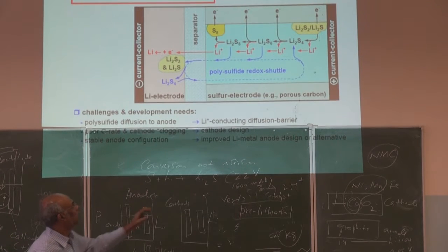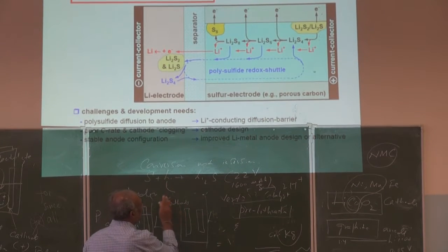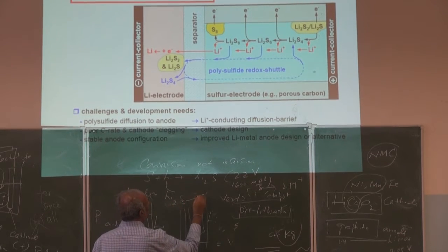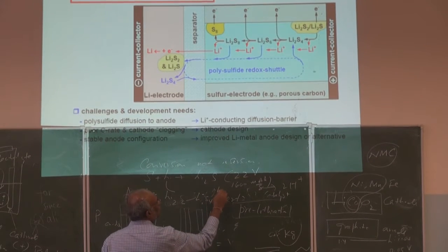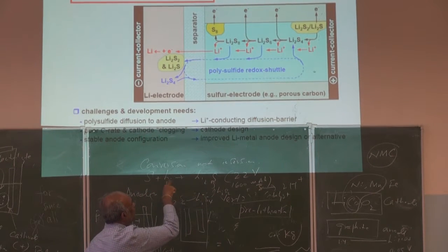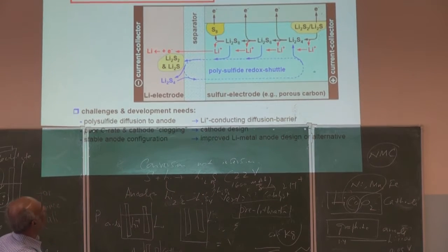But the problem is, before it makes this final product, it has to go through a lot of steps. It makes Li2S6, then Li2S4, and Li2S2, then it goes here. So it doesn't go directly from here to here. This is the initial sulfur, then it has to go 8, 6, 4, and eventually it makes this one.